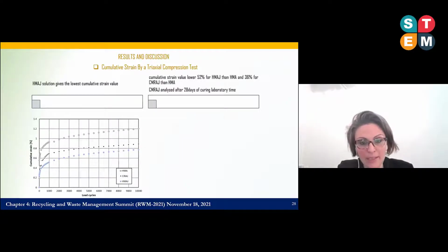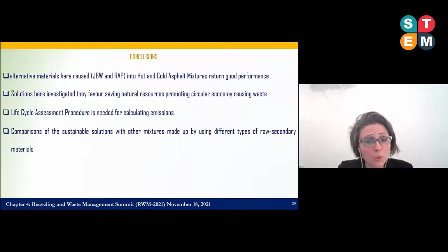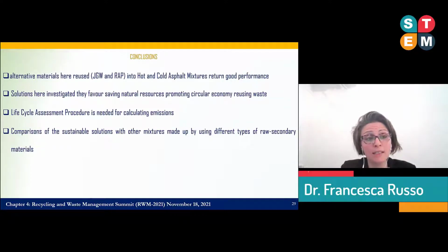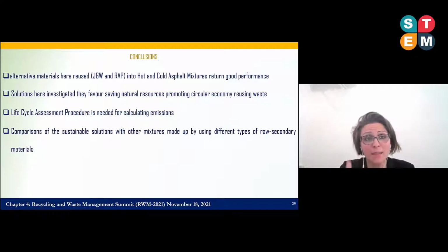So I just want to say that these alternative materials, jet grouting waste and RAP, can be used in pavements, in particular for making base layers of hot and cold mixtures, because they return a good final performance, both carrying out static and dynamic tests. Static tests in laboratory such as indirect tensile strength, dynamic tests like stiffness modulus and creep test.